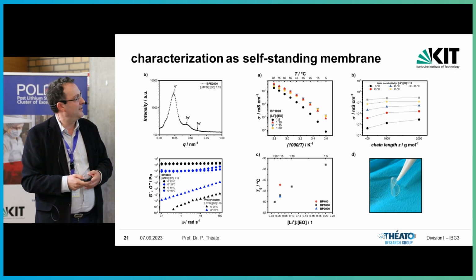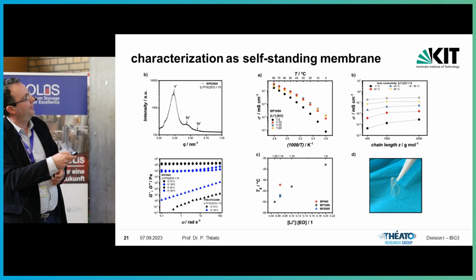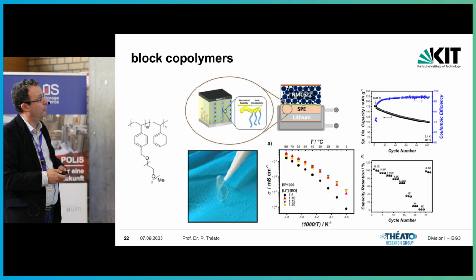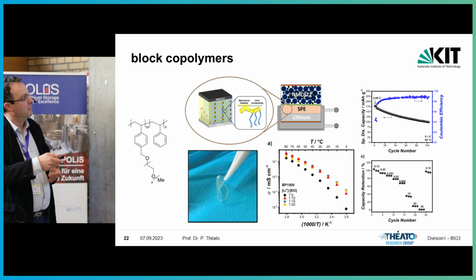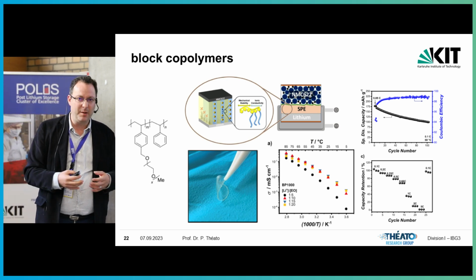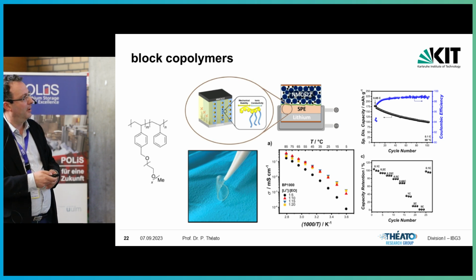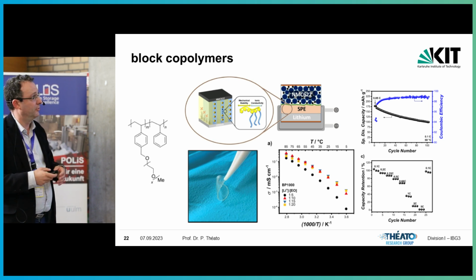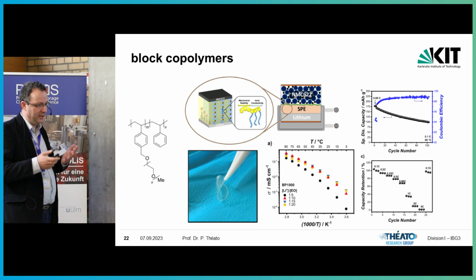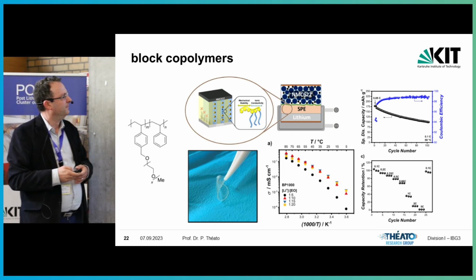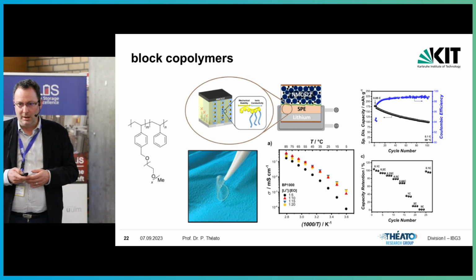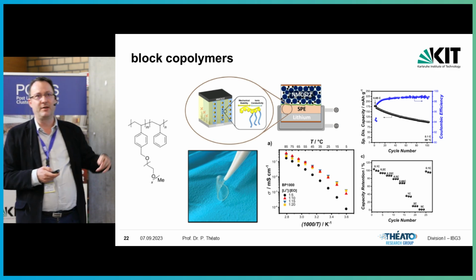You can make full cells out of this one. So Andreas did this against NMC 622, and you can see the cycling data here. It looks, at least for us as synthetic people, quite good and promising. There is a C-rate dependence, as typical, but all in all, this looks like a very helpful and promising thing. So we like that.